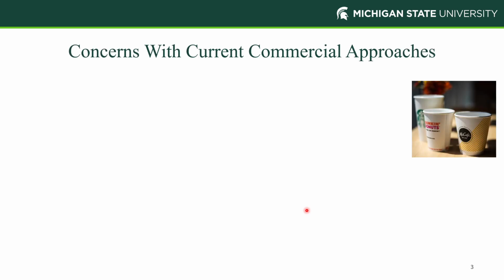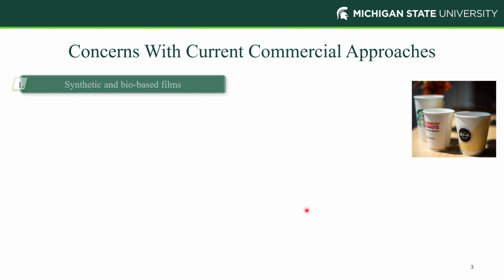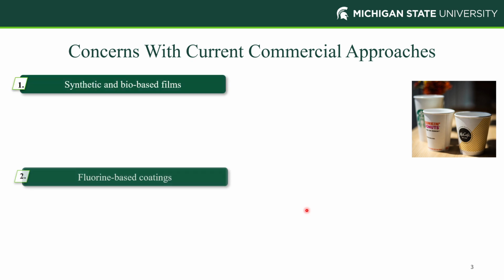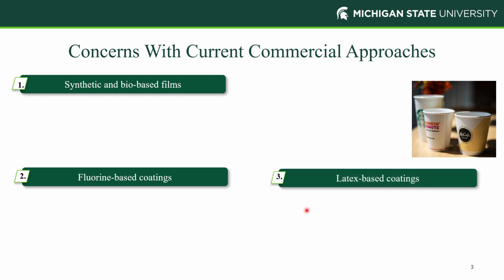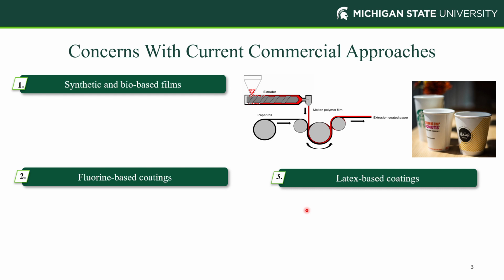So our motivation behind this research was to develop alternatives for the current commercial approaches that exist in the market, which are majorly synthetic and bio-based films, fluorine-based coatings, and latex-based coatings. And the major disadvantages with this, starting with synthetic films, are that they are basically plastic films that are extrusion laminated onto the paper, and hence the recycling is very difficult because it's difficult to separate the paper and the plastic film. And the presence of plastic on this paper also leads to generation of microplastics when these packaging materials are landfilled or dumped as waste.